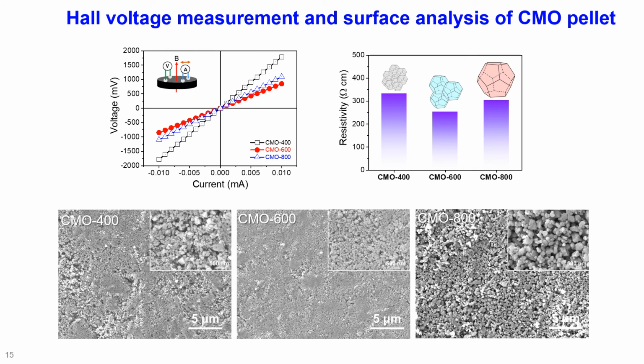We made CMO 400, CMO 600 and CMO 800 pellets to study the electrical conductivity of our samples via Hall voltage measurement. It confirms that the CMO 600 electrode possessed a very low resistivity. That means the higher electrical conductivity than the other two samples. And the surface analysis of the pellet is also shown here. Here the smooth and uniform surface has been obtained for the CMO 600 pellet, which is due to the optimum particle size and very less aggregation.